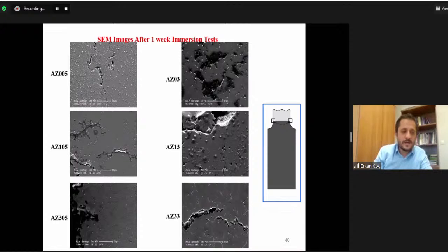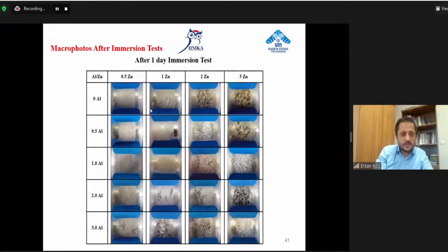Corrosion progresses towards the interior through the intermetallic phase. You see here what the intermetallic phase made? Very bad corrosion progress, because the intermetallic phase accumulates in the grain boundary and it weakens the alloys. And it's clear from these tables that the surface damage that occurs in corrosion increases dramatically with the increase of both the zinc ratio and the aluminum ratio.